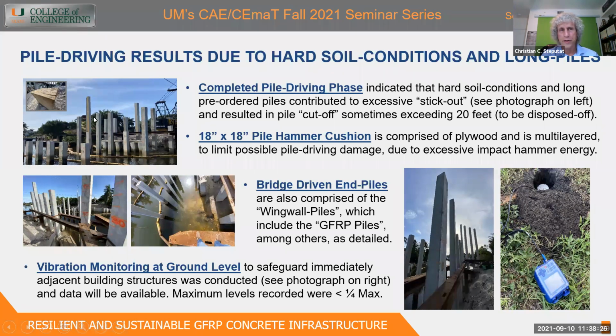I basically cut off the driving between 750 kips and 1,100 kips. We only needed, again, 200 for some of these. So it was definitely above what's needed without damaging the piles. If some people drive too much, you could say, well, you could have got 2,000. Well, not really, because you're inducing driving stresses that will crack the piles, and you're causing more damage than good. And you can actually shear the piles off underground and drive the top portion of the pile next to an existing one, voiding the pile and requiring more corrective action work.